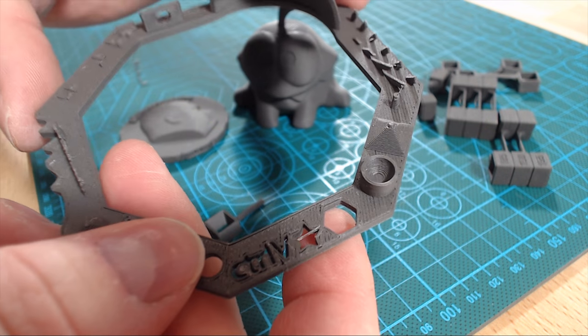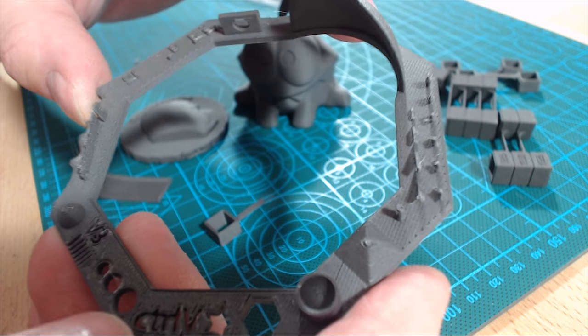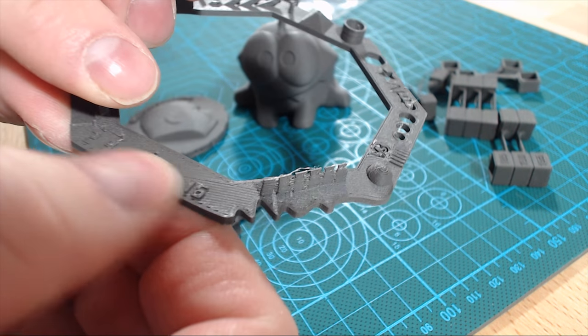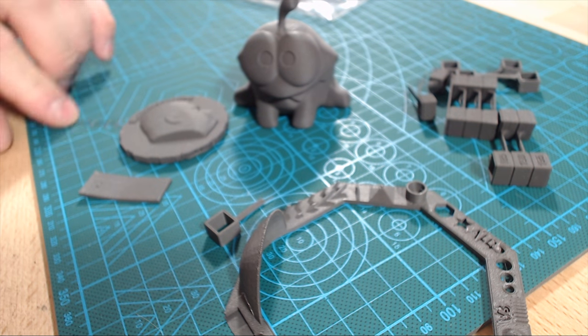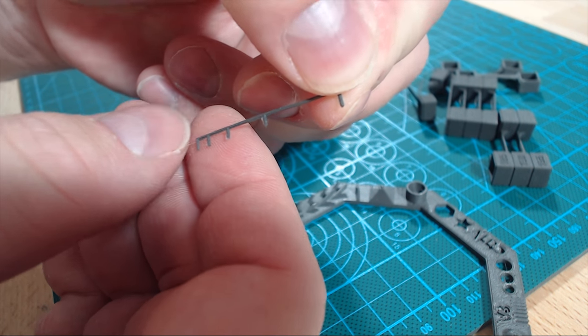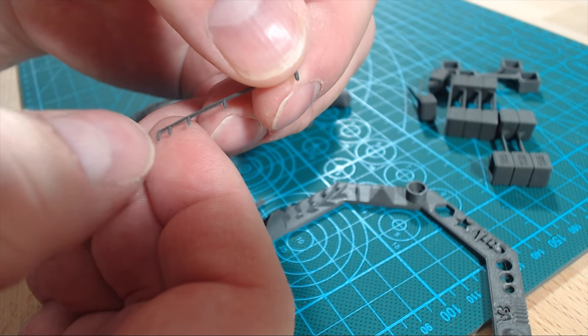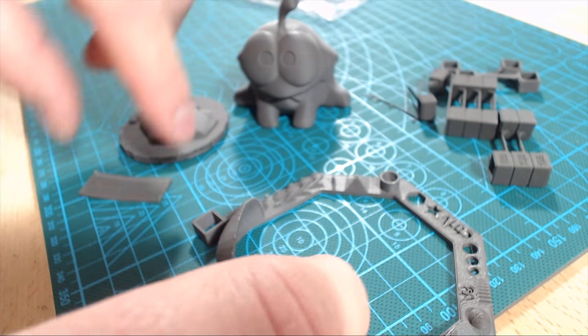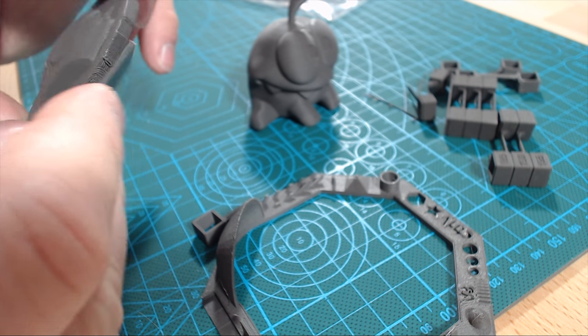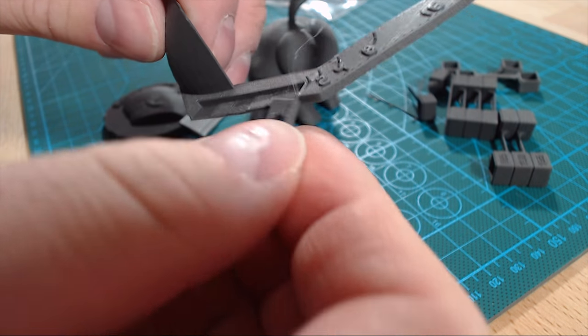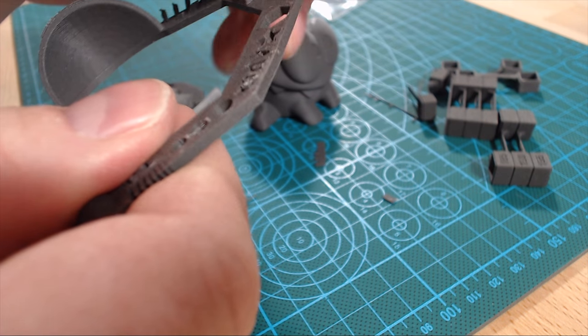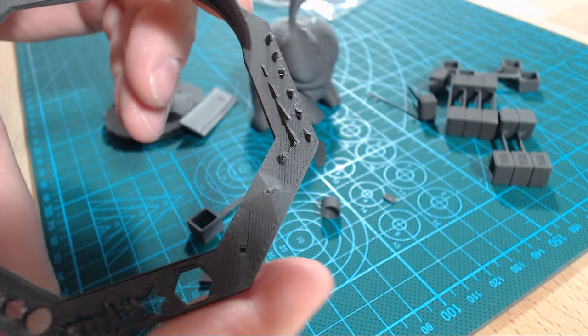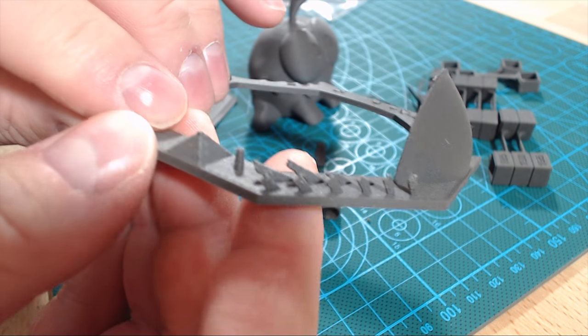And I printed this test as before. And it had very good result. I also broke off the bridge test here but they came out really nice. The piece is here and it's without any issues. It's a very thin piece so it broke off very easily. And that may be the one issue. The pieces break off really easily. So layer adhesion is maybe not very good in 190. But the print quality and overhangs here came out really well.